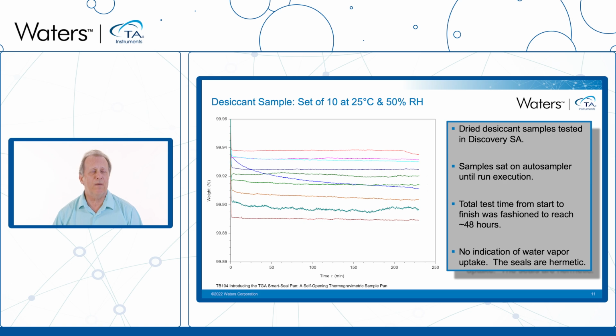So obviously seal quality is of critical importance here. And so first I want to use a couple of slides here to demonstrate the seal quality for these pans. What I have here is a set of 10 runs in which a desiccant sample was tested inside of a Discovery SA. Desiccant materials obviously are materials that will absorb water. So these materials were dried and sealed inside of the TGA Smart Seal pans, placed on the autosampler tray, and then run sequentially inside of the Discovery SA. The Discovery SA is an instrument that allows us to expose pans to specific temperature and relative humidity conditions. In this case, all 10 were left at 25 degrees Celsius and at 50% relative humidity for about 48 hours.